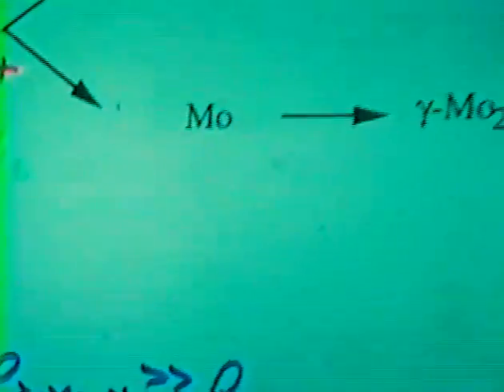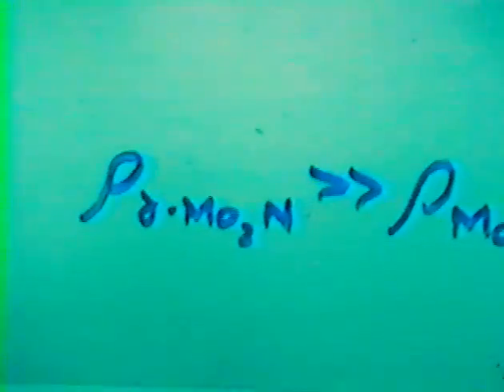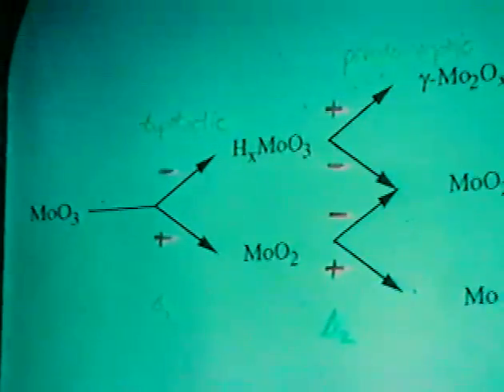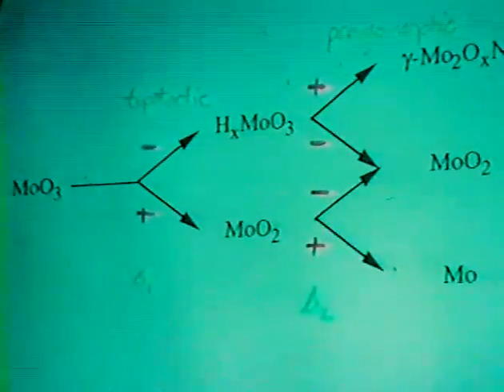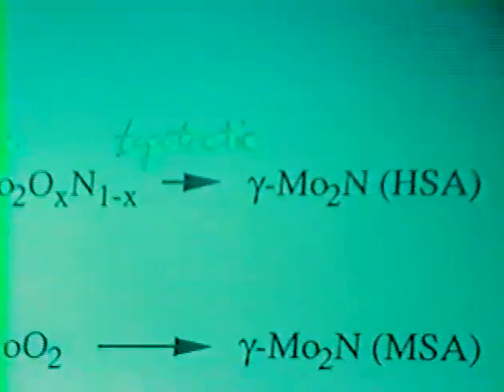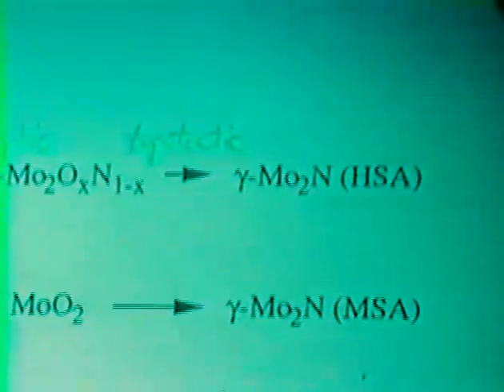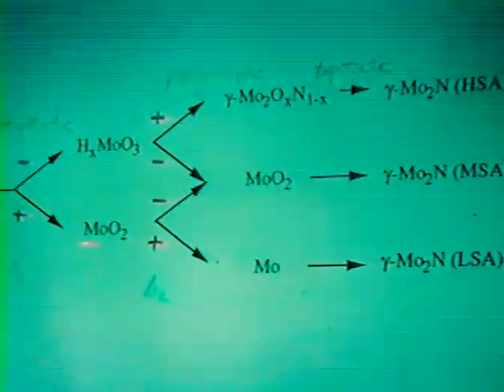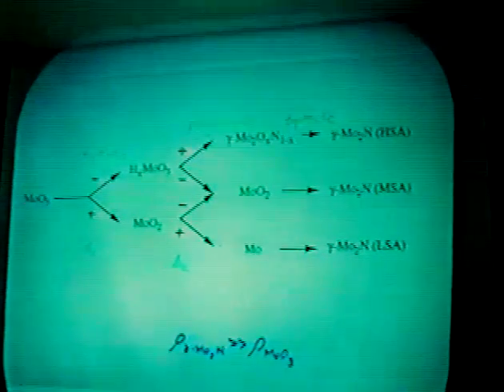The results of the experiments that I just discussed and some additional experiments using in situ X-ray diffraction and thermogravimetric analysis has led us to believe that there are a series of parallel pathways that occur during the nitridation of molybdenum trioxide. What's important here for this particular talk is not the individual species that are created, but the surface areas that you can produce. All of the materials in our case are predominantly this gamma dimolybdenum nitride. We see no evidence of the delta phase in any of the experiments that we've carried out.